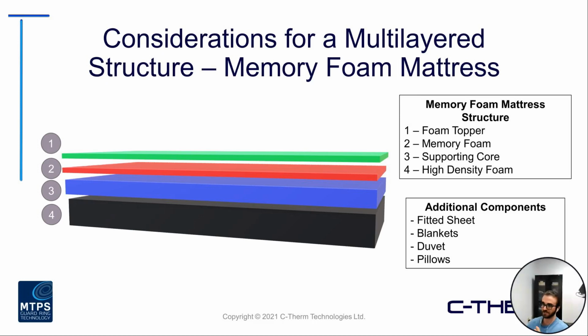But just taking a look at the foam layers here, one thing that you can do, if you're looking to get that pure effusivity measurement, is really take the measurement of the individual layers, which is what many groups that we work with do, and then take those values, whether it's the effusivity or the conductivity, and use that in different modeling softwares. I believe Adam mentioned, but we actually do have a talk coming up in November about how some of this thermal data is used in some of these modeling programs. I believe it relates to polymers more so, but still interesting to see how that data is used. But again, really taking the individual materials, understanding their thermal properties, and then using that to construct the most ideal sample or product that you're looking to develop.